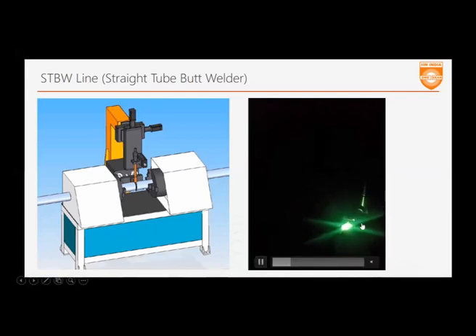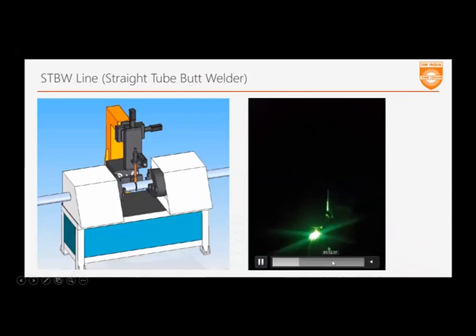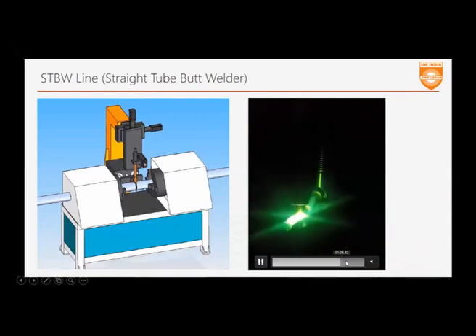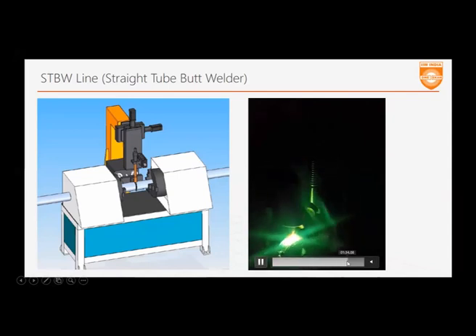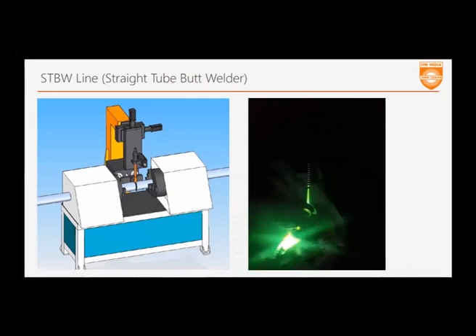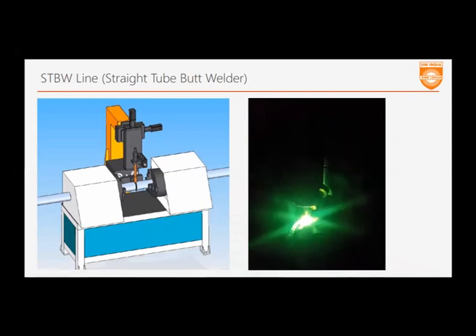You can clearly see that the torch is weaving. You can see that the wire is being fed directly into the pool and that the job is rotating in this direction. And let me see if I can quickly take you forward. Now, as you can see here more clearly, when you come to 360 degrees and are about to get over, you will have a slight overlap, which you can program up to 5 degrees, 10 degrees, depending on your job.